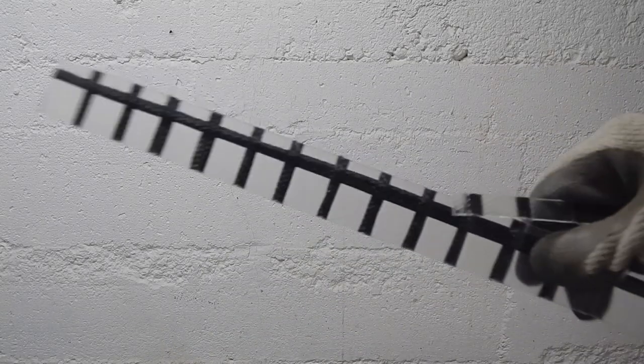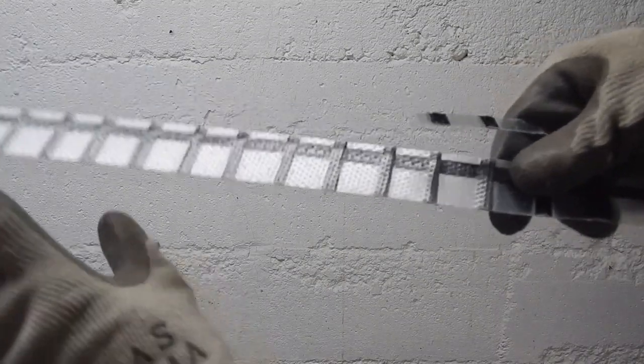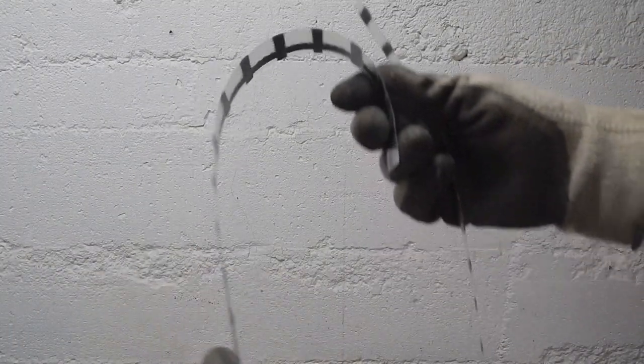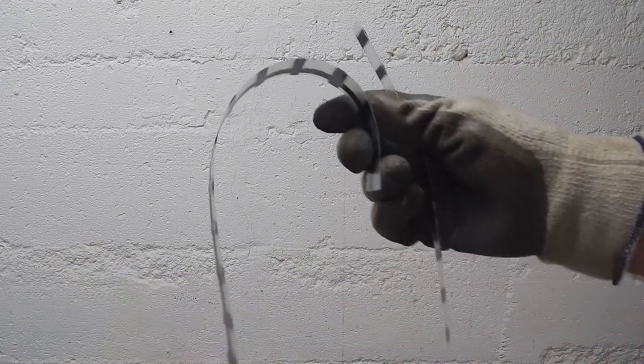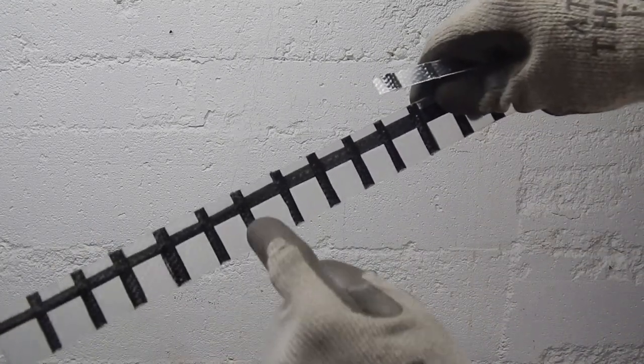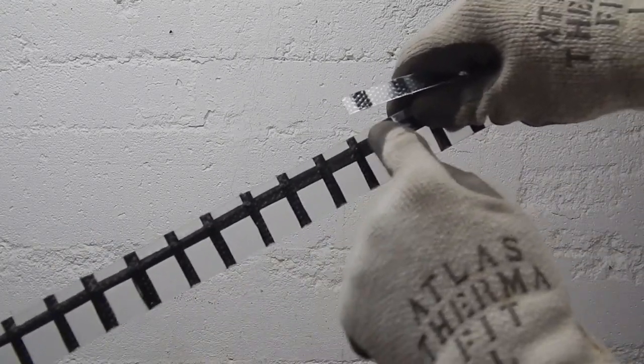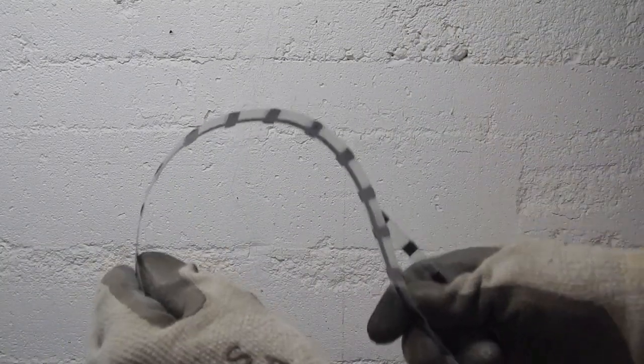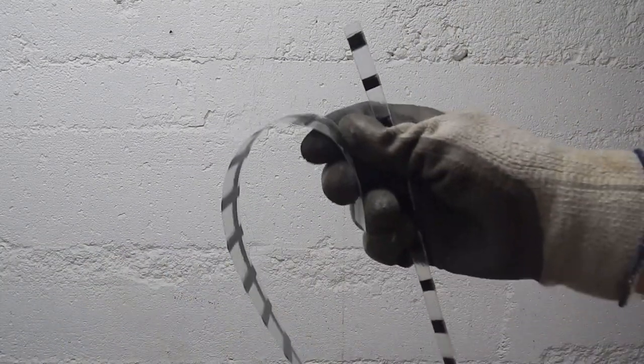These are some of the off cuts to show how relatively stiff it is. You can see some varying stiffness there depending on how wide the tow is. Where the tow is thin and therefore fatter top to bottom, the panel is stiffer. And where it's more spread out, the panel is thinner.